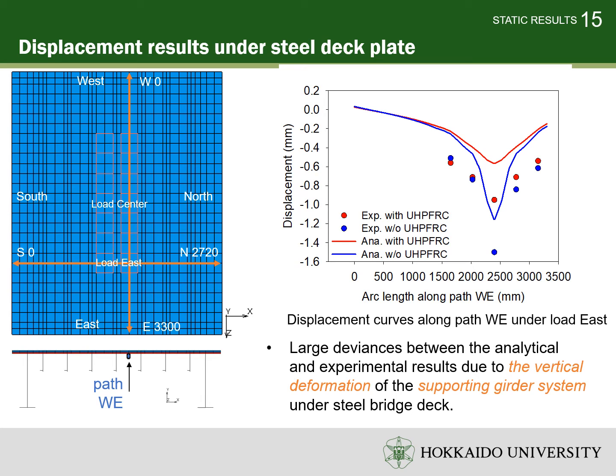The reason is that in the experiment, there is a steel beam system supporting the main girders of the steel bridge deck, and the displacement data from the bottom of the steel deck are collected by the LVDT measurements which are placed on the supporting girders. Under the wheel load, the supporting girder has been deformed in vertical direction combining with the other deformations from the connections of the supporting steel members. This leads to the higher values of displacement data from the experiment compared to the analytical model.